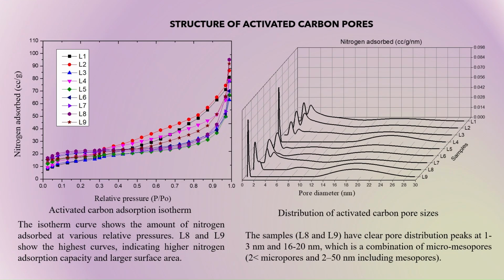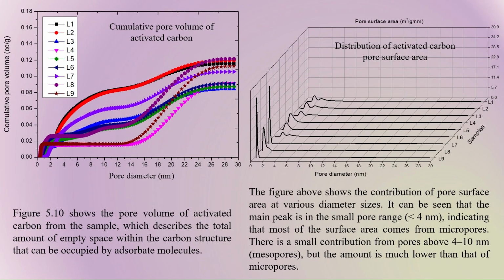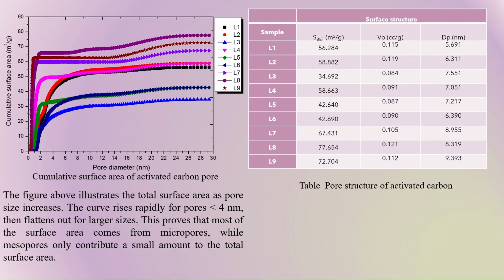SEM images show improved pore development at higher activation temperatures and appropriate holding times, supporting enhanced absorption performance. Samples L8 and L9 exhibit the biggest absorption capacity, indicating larger surface area and better pore accessibility. Pore size distribution is dominated by micropores with contribution from mesopores, which is favorable for methylene blue absorption. Micropores contribute significantly to surface area, while mesopores enhance pore volume and mass transfer efficiency.